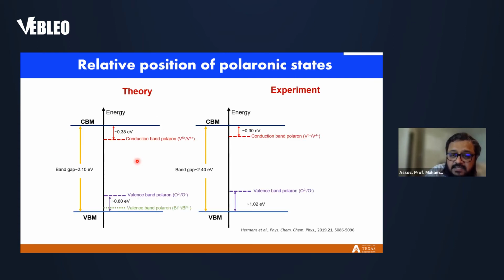Now, a summary of this polaronic result compared with experimental results from our collaborator: if we consider the band gap, again, the band gap is smaller in our computations. However, if we consider the polaron state formation, electron polaron and hole polaron, the energy values created below the conduction band, 0.4 versus 0.3 electron volt, hole polaron formation, 0.8 electron volt versus 1.02 electron volt, they do compare well between our theory and experiment.